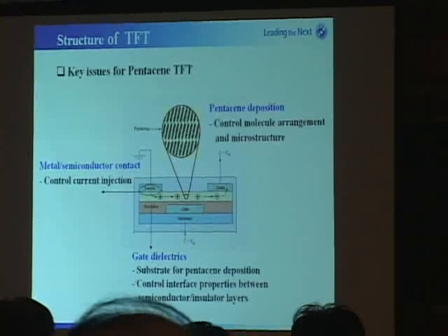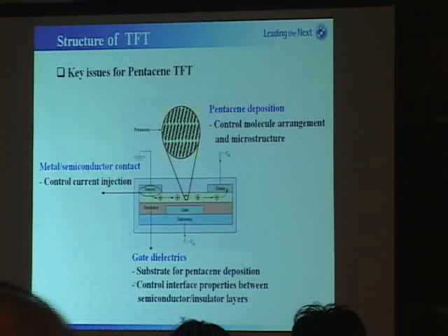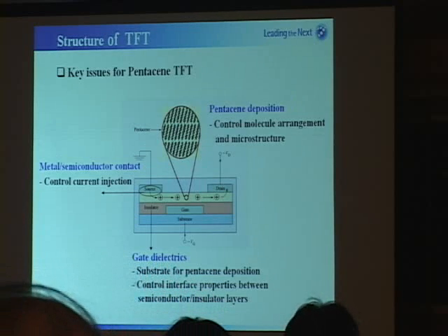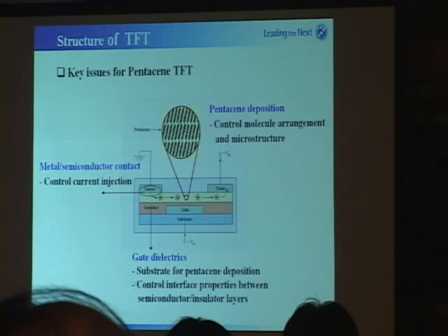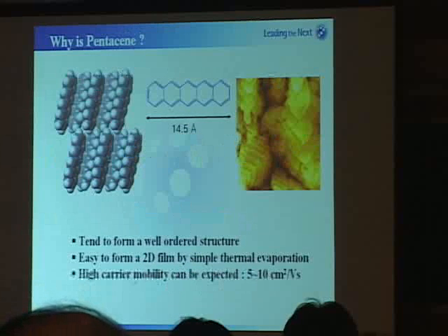Metal semiconductor contact controls the current injection, and gate dielectric is a substrate for the pentacene deposition, and controlling interface properties between semiconductor and dielectric shows a high performance for TFTs.